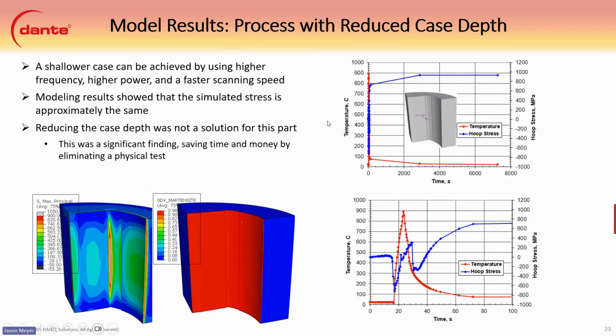Okay, so the next model we did was the one with the reduced case depth, and the idea here was the customer believed that less transformation would cause less tensile stresses and probably reduce the cracking. They never ran one like this, so they wanted to see a model first to see if it could help solve the problem. The model results show that the simulated stress is approximately the same between the baseline model and this reduced case depth. And this is a pretty significant finding for them that saved them a lot of time and money by eliminating an actual physical test.